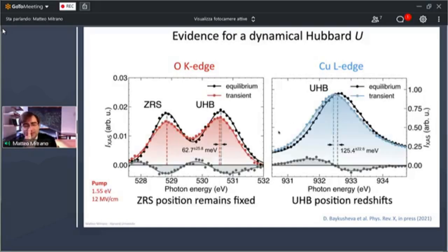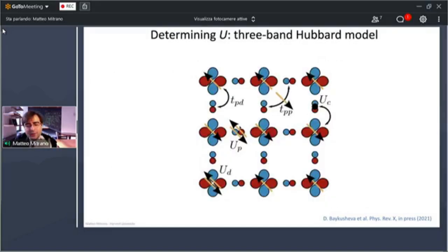We excite the material with the laser, and we see that the upper Hubbard band is actually redshifting and is changed by the application of a laser pulse on extremely short time scales. This happens essentially instantaneously and decays over time scales of the order of a few hundred femtoseconds. While the Zhang-Rice singlet is unaffected. So this is actually really important because it's telling us that the electronic structure of this material is changing. And we can actually rationalize this by mapping this electronic structure onto a 3-band Hubbard model. That is the minimal model that allows us to describe the electronic response of this material to X-ray absorption.